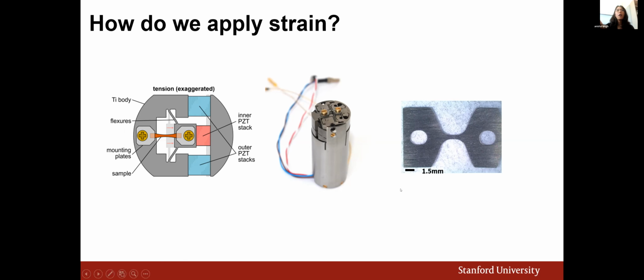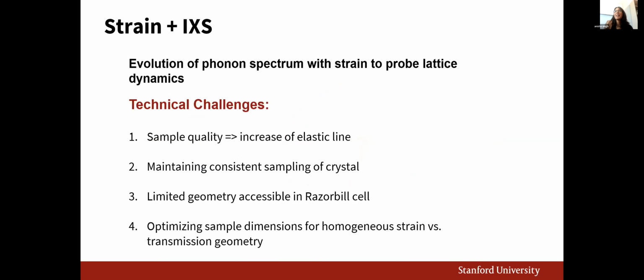All right. All that being said, though, there are still a lot of technical challenges that we had to consider as we start integrating strain tuning into IXS measurements. So this is a really interesting way to now probe lattice dynamics and how that evolves as we apply strain. But one of the main challenges, again, as I mentioned in the previous slide, as we're working particularly with very thin, very mechanically delicate and soft samples, sample quality is going to be a big issue. So these samples already don't have great crystallinity, and it's just going to get worse, right? As we repeatedly strain the samples, we're going to see a broadening of our Bragg peaks, and ultimately it is going to result in an increase of our elastic line.